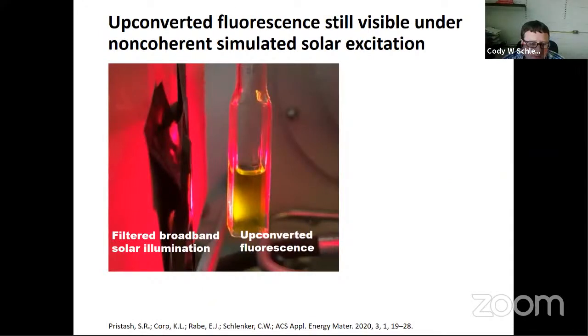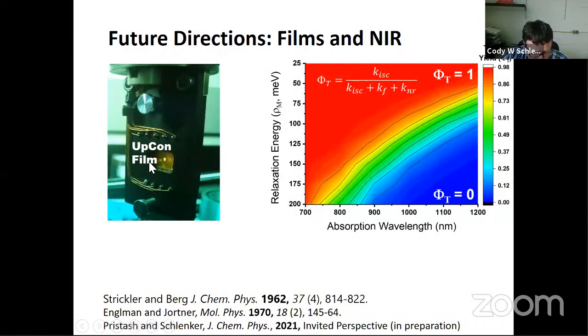One of the attractive things for solar energy applications is that you can do this under broadband excitation. So this is a solar simulator here with a red filter. We basically have a long pass filter here that just lets red light through from the solar excitation, and then here is the emission from our conversion material. You can also put these molecules into a film. So here is a film in our device chip where we're shining a red laser onto the film. We've got a color filter on the camera here that allows us to block out the laser excitation, so you can see the upconversion coming out of the film there.